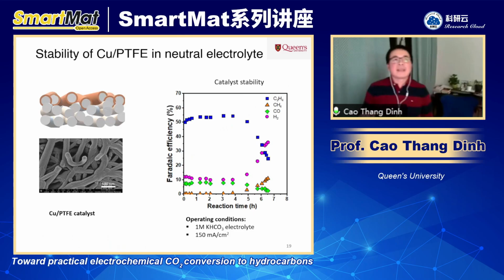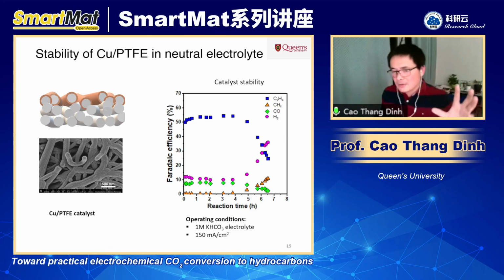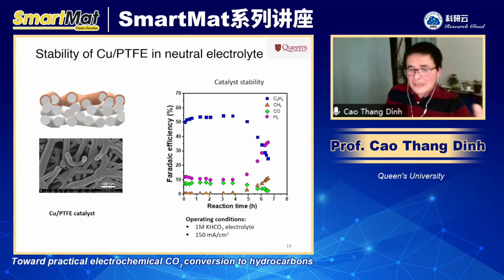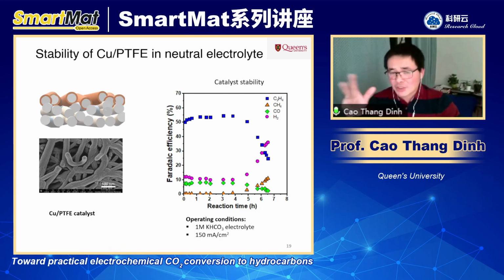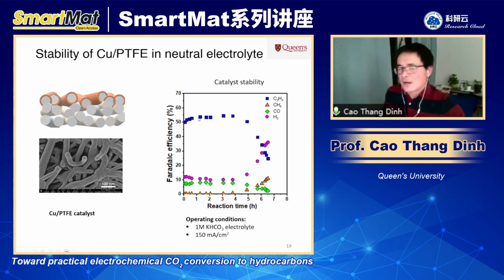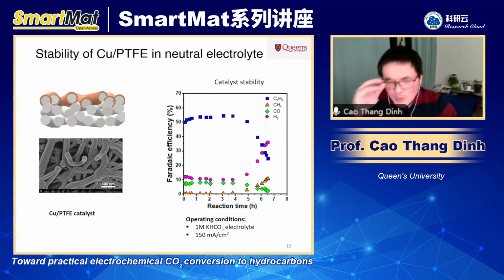So we started working on that just by checking the copper on PTFE. We use the same catalyst there, but we do not coat it with carbon. Even without the carbon layer, the copper on PTFE can work as the electrode. We use the substrate here, and then we run the reaction, but now in a neutral condition, trying to avoid carbonate formation. We still observe a decent ethylene selectivity of around 55%. But the problem now is that we can only run the reaction for only 4 to 5 hours.